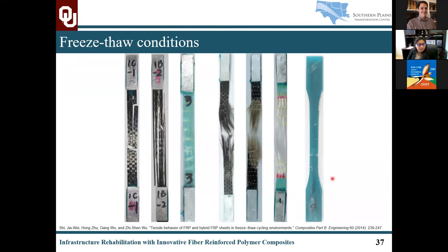This work has been seen in the past literature where FRP composites are in a state of stress in real strengthening applications. And with respect to the service loads during the freeze-thaw cycles, cyclic thermal stresses on the fiber matrix interface are likely to be magnified, and there are more microcracks that can be developed due to these freeze-thaw cycles. So the consideration of combined effects of harsh environments as well as service loads is very, very important to understand, and the behavior of FRP in this application is really the need of the hour.